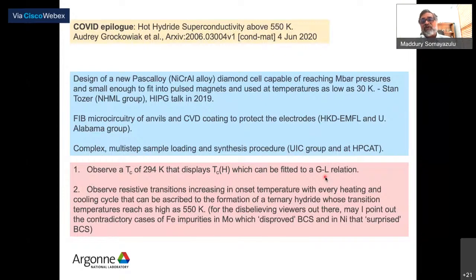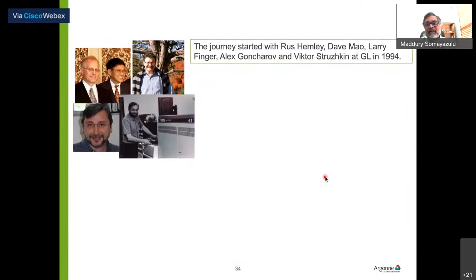Now, of course, we don't have all the details, and all we do know at this point of time is that it certainly is a lanthanum hydride based system. What else is in there, we don't know, but it most probably looks like it's not a simple binary system anymore. And that is borne out by a lot of theoretical calculations which are coming out, which say that, with ternary systems, for example, there is a theoretical and an experimental paper on the yttrium lanthanum system. There is a paper talking about the lanthanum borohydride hydrogen system, and so on. But it turns out that you could actually manipulate ternary and quaternary systems, based on the same idea of hydrogen content, to achieve higher and higher temperatures.